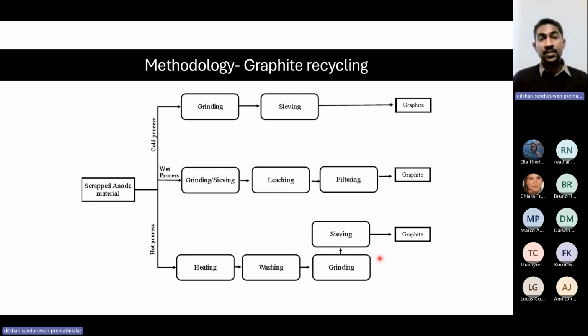So here, in this slide, you can see how I did the optimization of the 3 different methods that I used for the recovery of graphite. For the physical recovery, or the cold process, I optimized the grinding period because I used a grinding and sieving based treatment process to recover graphite. So here I tried to optimize the grinding time and also the sieve sizes. When I optimized the grinding time, I identified that 2 minutes is the best time for this grinding, because if I grind it for more than 2 minutes, I find lots of copper particles in my fine fraction, which means the carbon content is going to be quite low. The same thing happens when I reduce the time, because at reduced times I'm going to have a smaller amount of graphite or carbon material in the fine fraction, because it's not going to liberate all the graphite available in the anode active material.